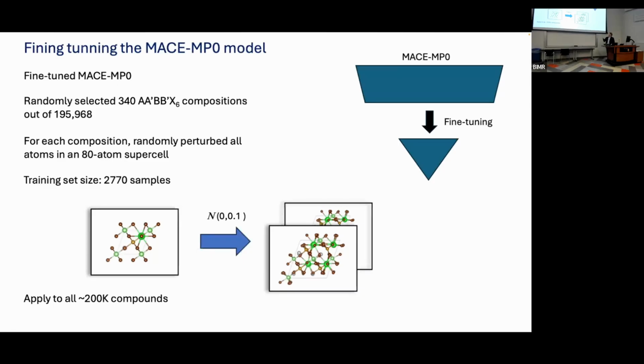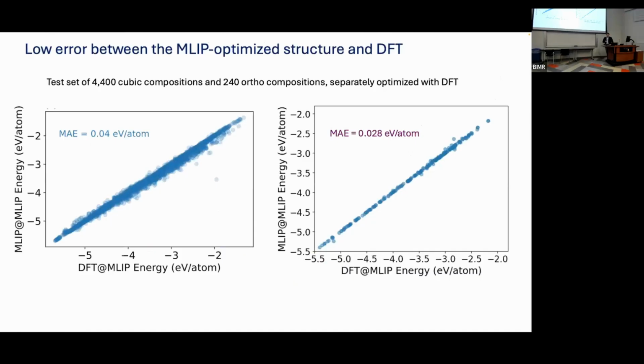And this is a relatively small data set from a computational perspective, and then we applied it to a much larger space. And how does it work? So here, this is the MACE fine-tuned model relative to DFT, and these are structures relaxed. So this DFT at MLIP implies that we've optimized the structure with MLIP, and now we're comparing the DFT energy at that structure versus the MACE model at that same structure. And this is 40 meV per atom, which is a reasonable accuracy from our perspective for the formation energy.